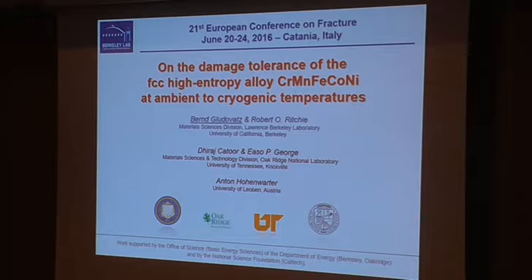The technique works in that way that we basically take two fracture surfaces, put them inside the SEM and take images under two different angles, which are then overlaid with a reconstruction software. So we create a 3D digital surface model, which we then use to put multiple arbitrary crack paths at this intersection from fatigue pre-crack, overload stretching zone and overload fracture zone, and then we need to find exactly the same crack paths on the second fracture surface, which is tedious and very time-consuming work, and this is really a lot of work to do.